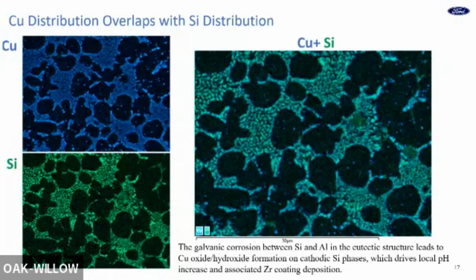So based on this simple test, we think the potential mechanism for the zirconium formation on the silicon is the galvanic corrosion between the aluminum layer and the silicon layer, and the oxygen reduction on the silicon layer promotes a local pH increase. Then the copper ions in the solution can form a precipitate like copper hydroxide oxide. Then the hydroxide can support a higher oxygen reduction reaction, further increase the local pH, and trigger the zirconium formation.